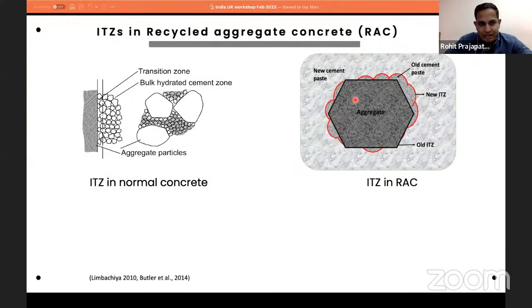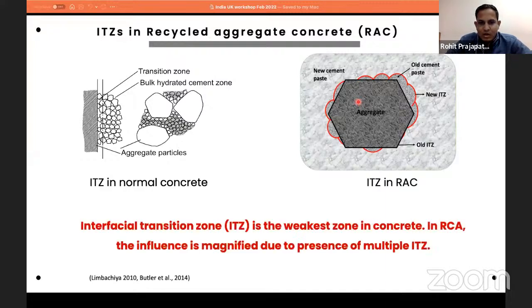So when you put these aggregates in the concrete, in normal concrete we usually have one type of ITZ, or interfacial transition zone, but in recycled aggregate concrete you have multiple ITZs. So the old ITZ between old mortar and aggregate, and there could be a new ITZ which is formed between the new cement mortar and the recycled aggregates. We know that these ITZs are the weakest zone, so the influence of ITZ is magnified in recycled aggregate concrete due to the presence of multiple ITZs.